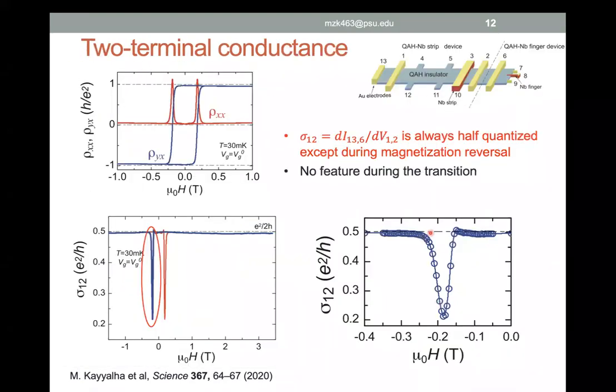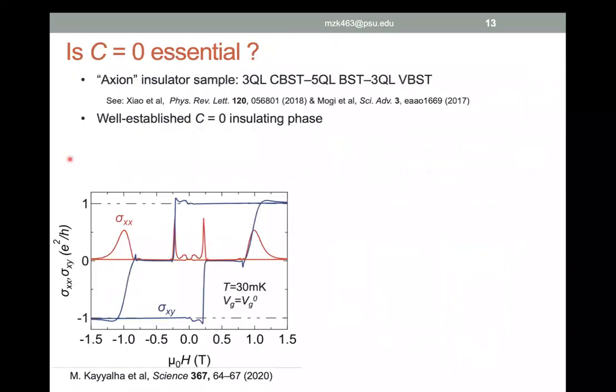Actually, there was another reason that this Science paper, the 2017 Science paper by UCLA, is crucial for the observation of Majorana, and that was the emergence of this C equal to 0 insulating phase. So in order to actually look into that, we also grew some samples that show a very well-established insulating state during the transition. These are what we call axion insulators. So they're like chromium doped and vanadium doped samples kind of stacked together.